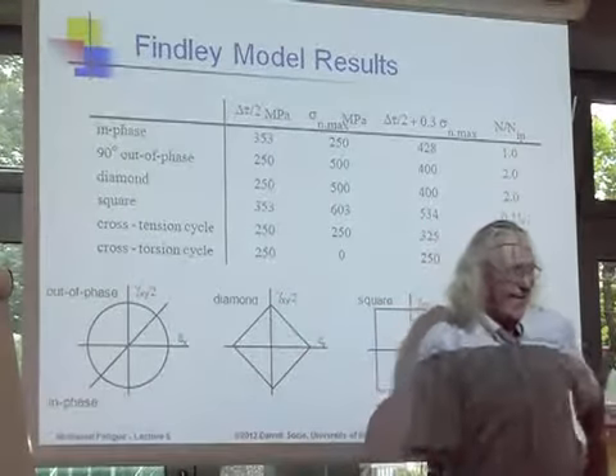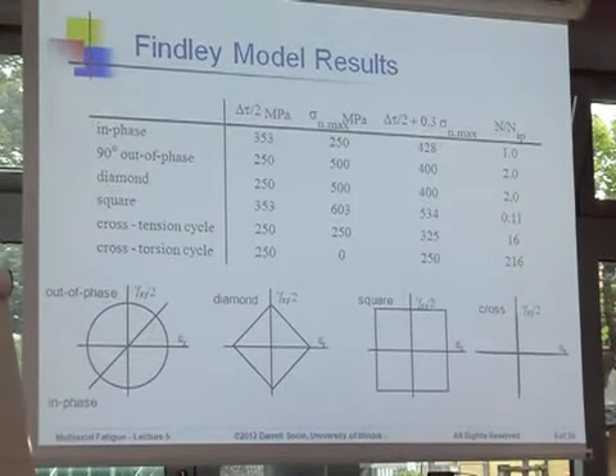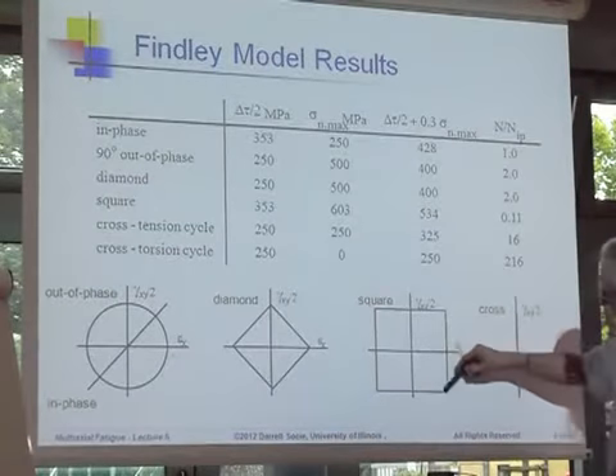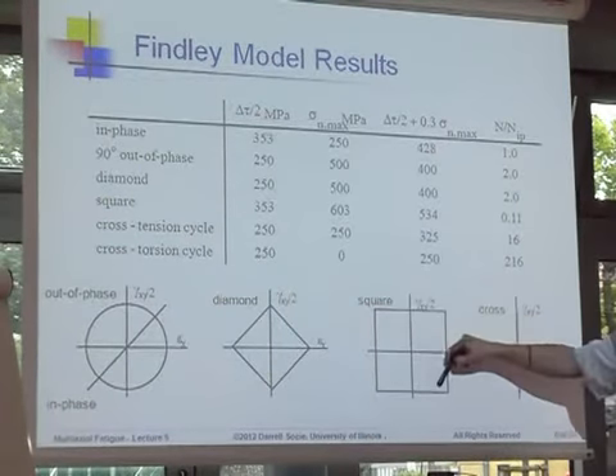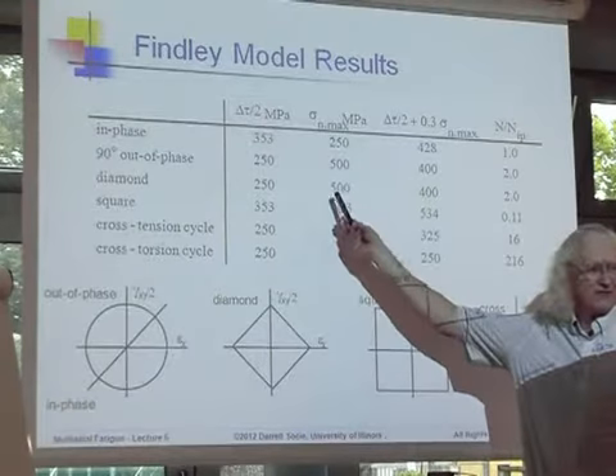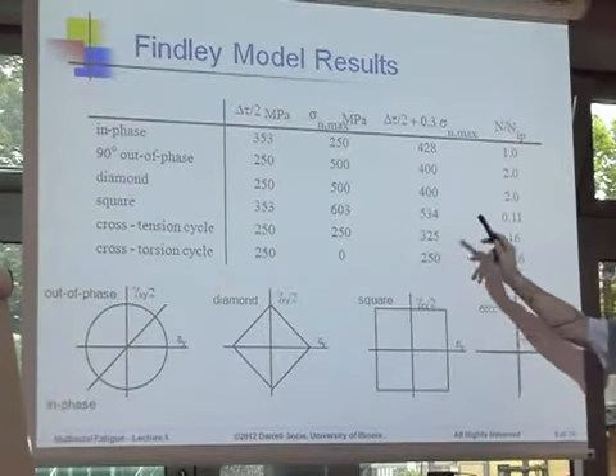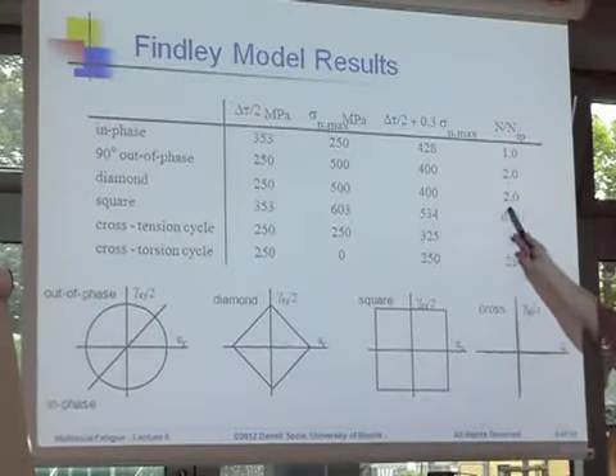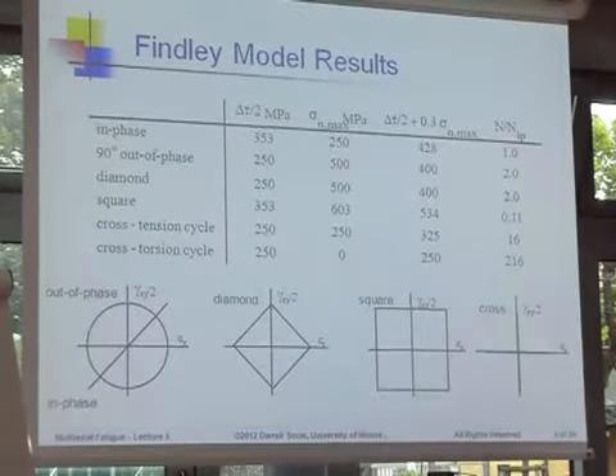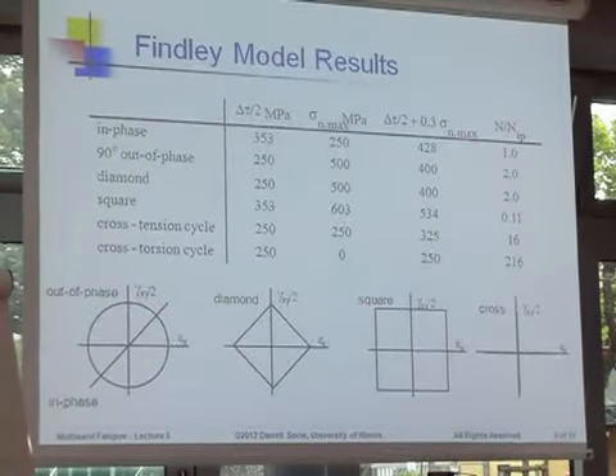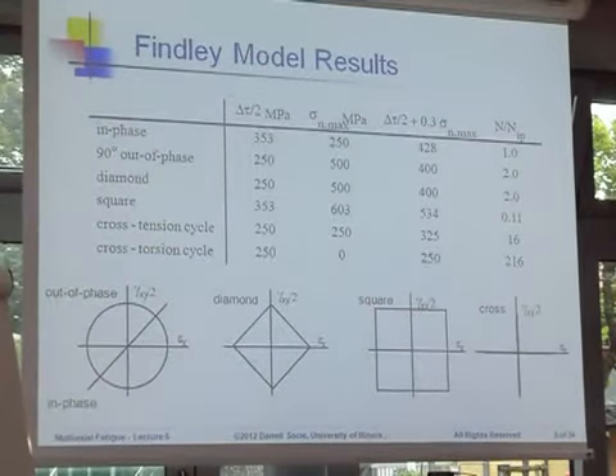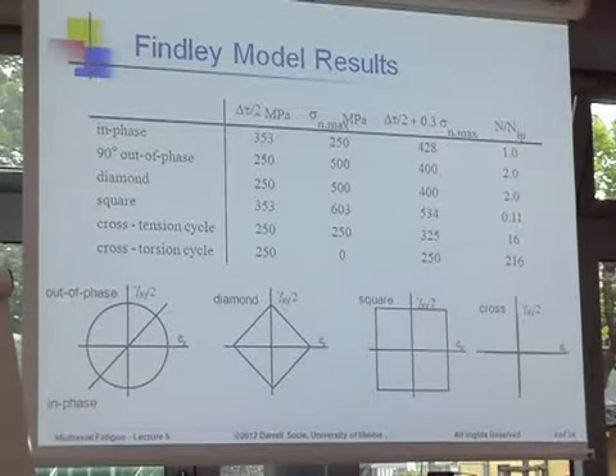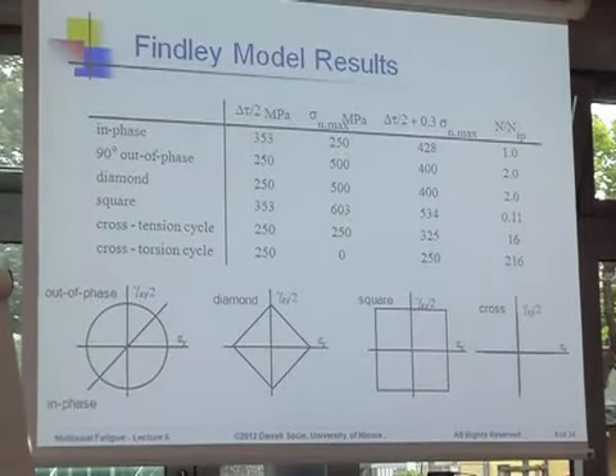Okay. And at the same time, it has the biggest range of normal stress. Right? So when I put the two of those together, it's a very big number, and of course the life is down by a factor of 10. And that's actually what we see in the experiments. And then finally, you can do a cycle of tension followed by a cycle of torsion, and here we see nothing happens.